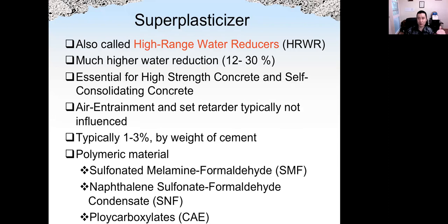We also have a so-called high-range water reducer, which can reduce the water content by 12 to 30%. For high-strength concrete or self-consolidating concrete, if we want very high strength by lowering the water to cement ratio, or we want to increase the slump to an extreme extent, then we want to use superplasticizer. Typically 1 to 3% by weight of cement. We have different types of superplasticizer. Again, they are all polymeric materials, such as sulfonated melamine formaldehyde, or SMF. Another one is SNF. The newest one is called PCE type, or polycarboxylate type. Very hard to pronounce, but the CE type is the newest type of superplasticizer.